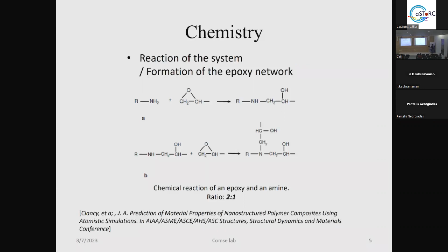You can see here the chemistry of the cross-linking process, and it is a 2-step reaction. First, the amine type of the hardener goes to the epoxide, and they form the first step of the subnetwork. The epoxide ring opens and takes the amine, and then this product links with another epoxide of another epoxy monomer, and that's why we need 2 monomers for 1 hardener. The ratio is always 2 to 1 because of the functionality 2 to 4. And we have the first subnetwork here after the 2-step reaction. Of course, this happens again and again in order to have a big, fully cross-linked network.